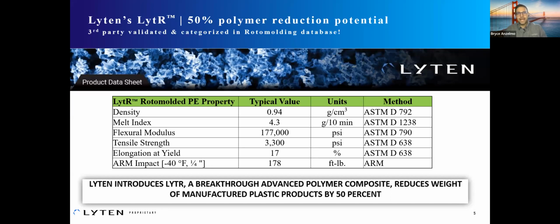Not only do we have our material that adds stiffness, but the real criteria here is, if you look at some of the standard mechanics, typically some of these stronger or stiffer systems don't elongate, or maybe they become a bit brittle. But what we've really engineered for is to keep the elongation of the base polymer similar or the same, in fact, by also getting that stiffness. So for those that know polyethylenes, they can be very stretchable, 800-900%. You can even max out the tensile elongation. We're also able to do the same with the flex modulus improvement with this solution. So again, that's taken us time to really develop and understand that and how our formulation plays with the polymer from the interface of our material, the 3D graphene, into the plastic.